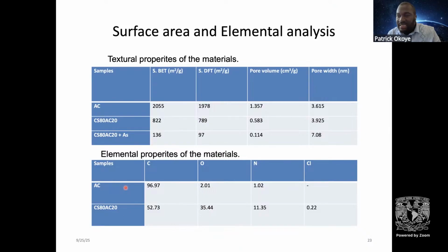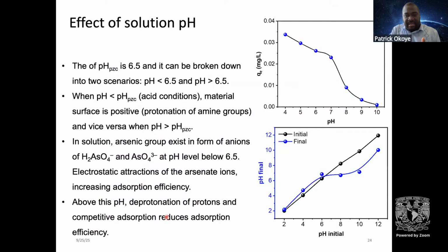Eventually, you could see that we have a carbon-rich material with the activated carbon, but adding the chitosan introduced the nitrogen group, some form of chlorine, and more oxygen. And hence, we have lower carbon in this. But why we did this is to ensure that arsenic is removed. And in a bit, I'm going to explain to you the challenge that we had.